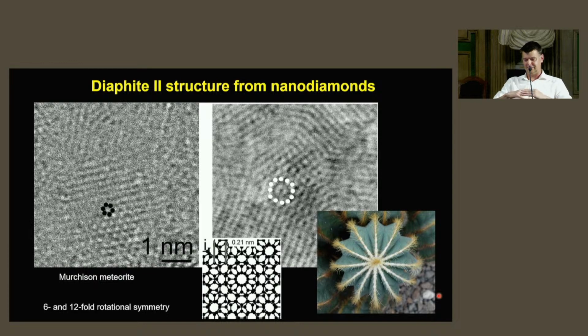But graphene layers can be rotated on top of each other, and they could form really interesting rotational symmetries. Here, if they are rotated at a twisted angle, they form this 12-fold rotational symmetry, which you will see on the right side of the image, which resembles the shape of a cactus. Anyway, so these are intergrowth structures, the diaphite structure.